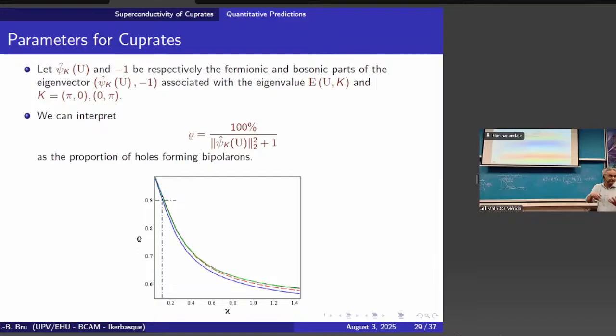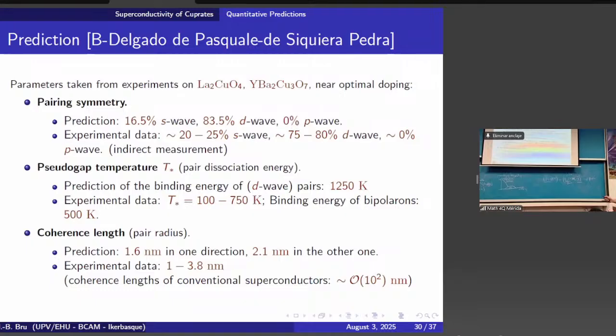But everything is a little bit bigger than the hopping amplitude in terms of electron volts, but smaller than the Hubbard repulsion, though of the same order. And doing this, what we find is the following. We find 16.5% of S wave, 83.5% of D wave, 0% of P wave. But this is not numerics, it's just a mathematical argument. Experimental data mean 20-25% S wave, D wave 75-80%, but these are crude estimates, and here P wave is 0%.